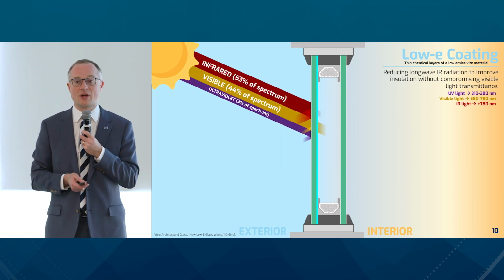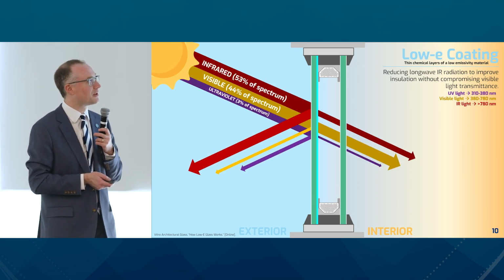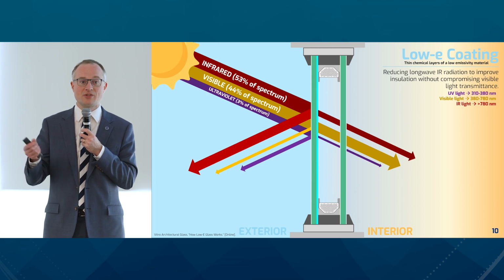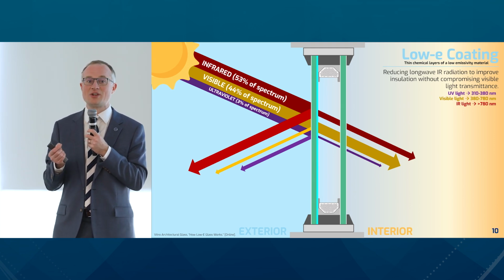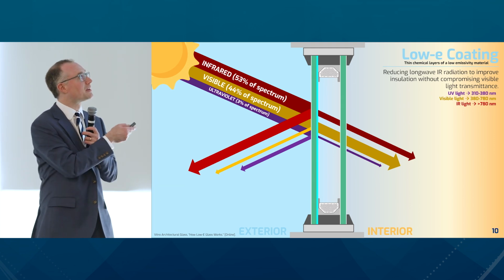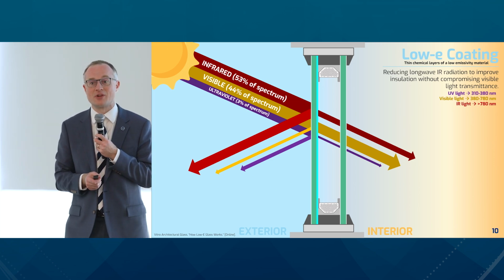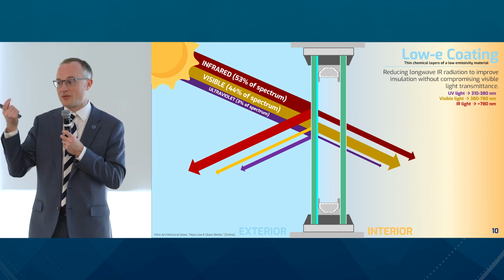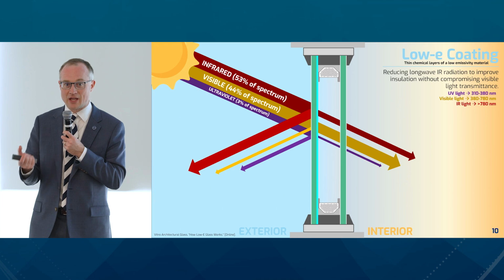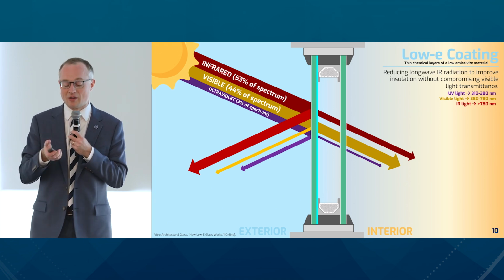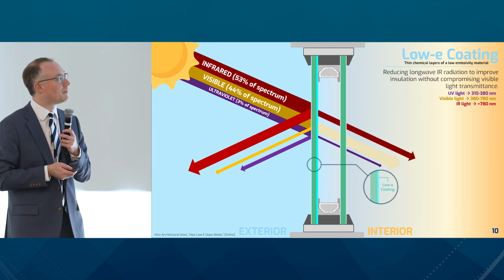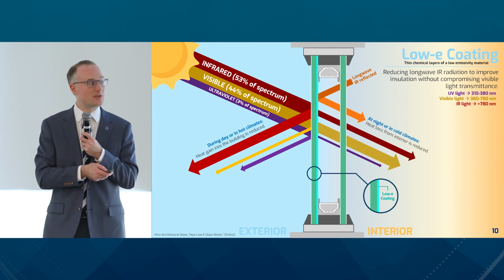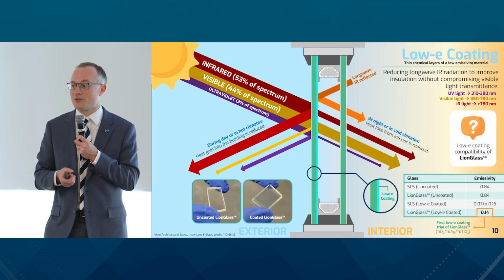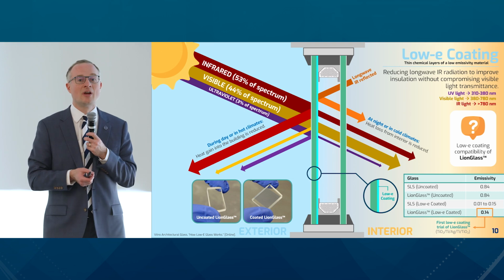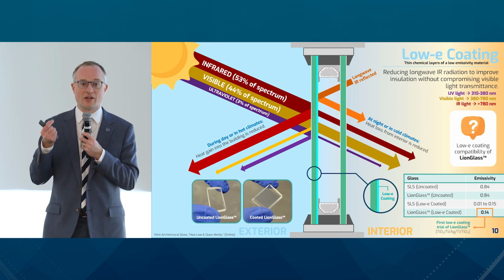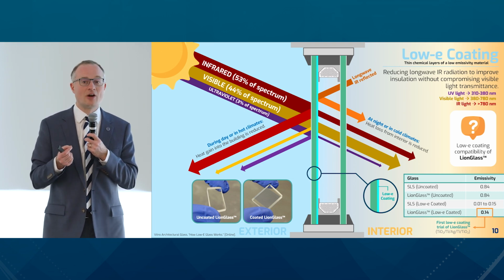So low E coatings are an essential part of architectural glazing. One of the goals of windows is to allow for as much visible transmission of light as possible while reflecting as much of the infrared and UV parts of the spectrum as we can to ensure that there's good thermal insulating behavior between the inside and the outside while allowing for good visibility. And so one of the technologies that is used is a low E coating. This is on the order of a couple tens of nanometers. Very thin layers of silver and/or titanium and titania are used.